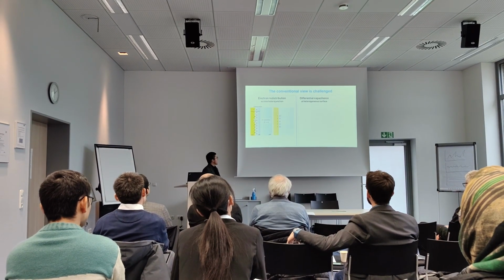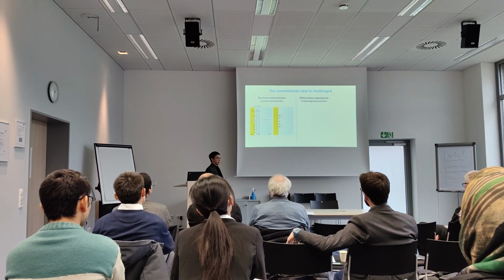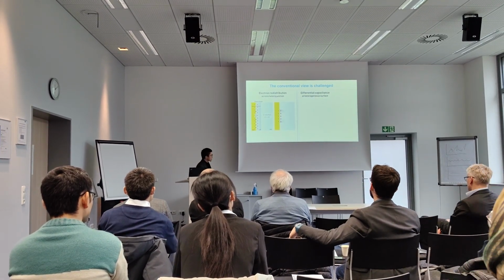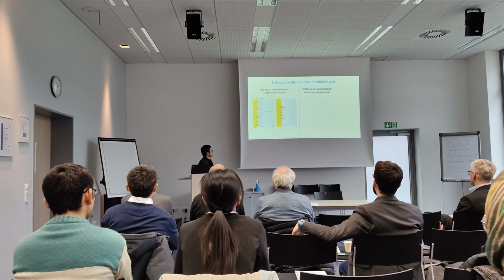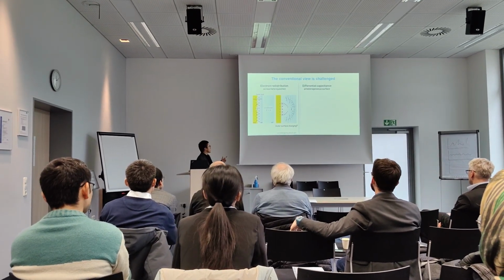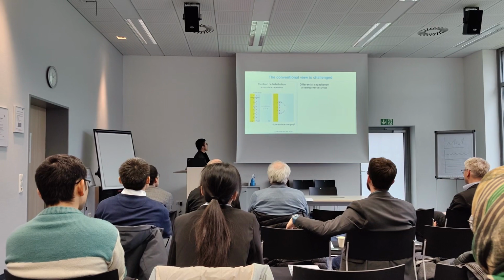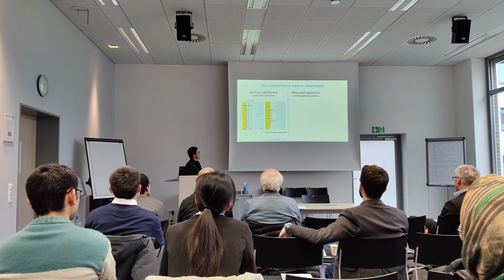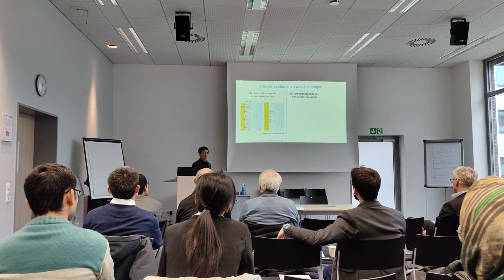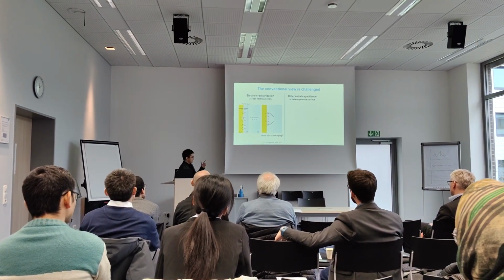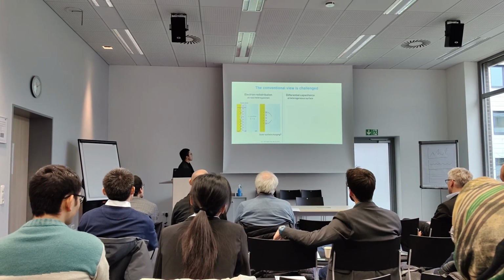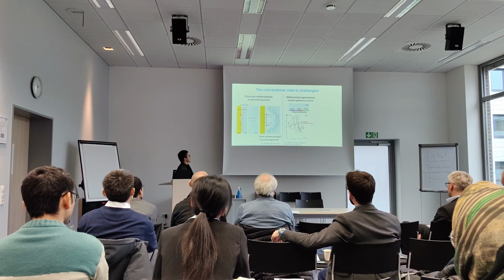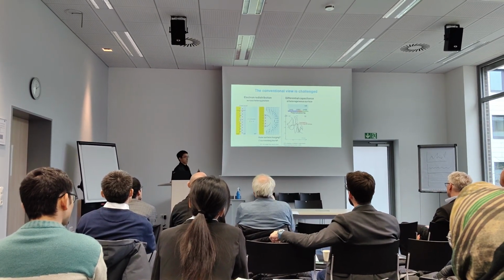However, in a real supported nanoparticle system, people adopt this conventional view, but several years ago, Dr. Tobias Weniger proposed that there might be outer surface charging at the particle-support interface surface, because the nanoparticle does not fully cover the support. Our result reveals that, because of this outer surface charging, there is an electric field surrounding the heterogeneous surface, and I will discuss it later in detail.